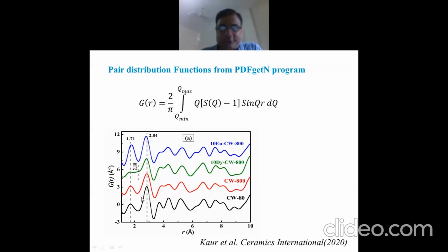If you measure the X-ray diffraction patterns and then do the pair distribution function analysis, you will find this second peak around 2.8 angstrom is missing, because X-rays cannot detect the oxygen atoms due to the weak scattering of X-rays from low Z elements like oxygen. Whereas neutrons are very good for finding the structure of oxide materials because they can determine the oxygen atoms also very accurately.